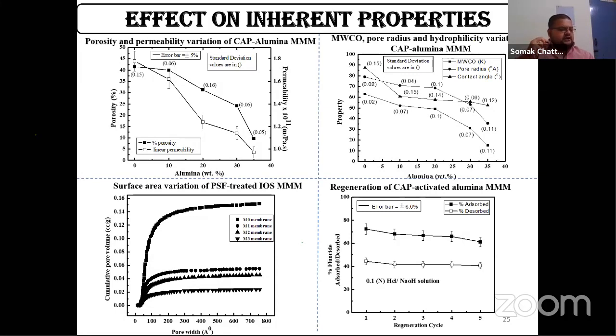Now, there is an important conclusion in this case. You might be thinking that the permeability is getting reduced, whereas the hydrophilicity of the membrane is getting increased by the reduction in contact angle. How is that so? Am I speaking a lie? Now, that is not the case. In this case, if the permeability gets reduced, that is due to the discontinuity of pores or the blocking of pores on the top surface of the membrane.